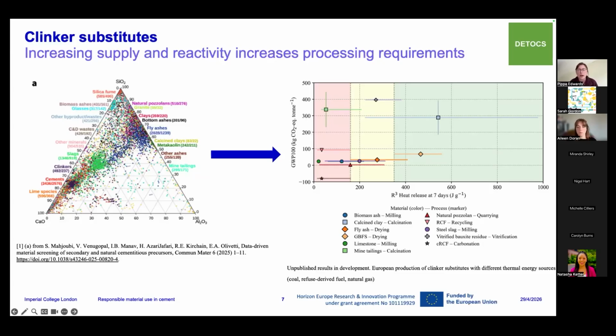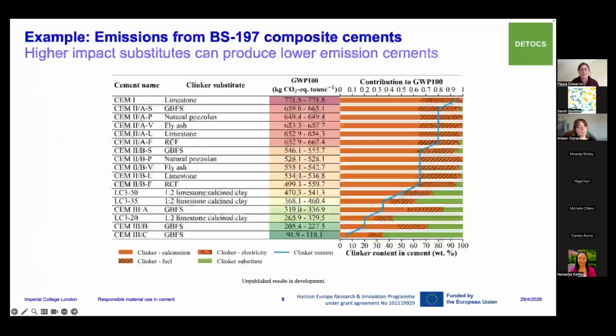But by using R3 heat release as a proxy for reactivity and comparing reactivity and emissions from our LCA data, we can identify materials which might have good performance as composite cement mixes, like calcined clay, which has both high reactivity but also relatively high carbon footprint compared to the other substitute materials. Even so, the higher emission clinker substitutes roughly have half the emissions of clinker. So replacing the clinker with these materials will reduce the overall impact of composite cements.